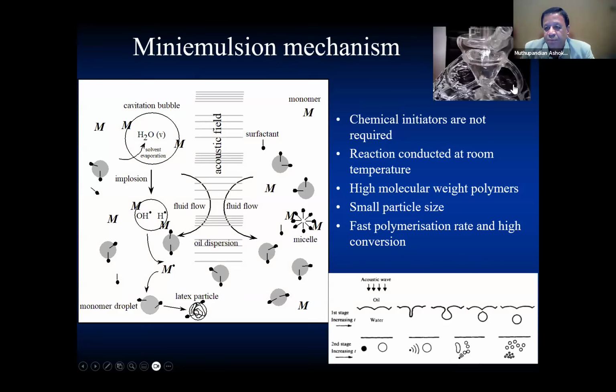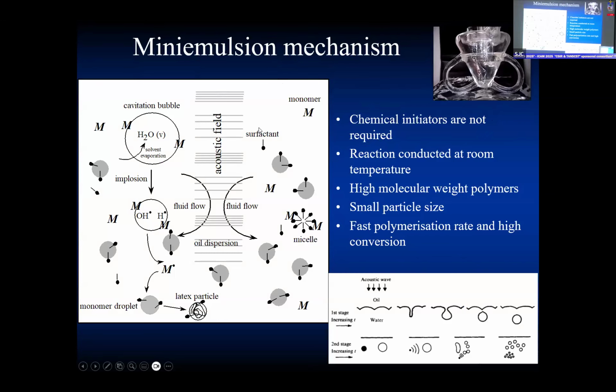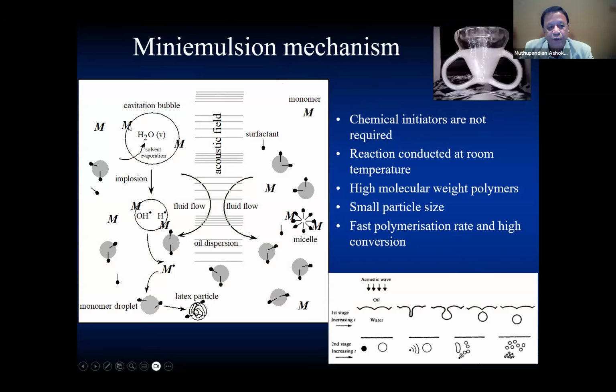So I think I already showed you the picture of how to make an emulsion, for example. When the monomer is dispersed using this emulsification process that you saw, you get the monomer droplets, and then you have, in water, cavitation bubbles generating radicals. Radicals then can react with the monomer to generate monomer radicals. The monomer radicals can diffuse into the monomer droplet to convert them into polymer particles. So by controlling the size of the monomer droplet, I can control the size of the polymer and also the molecular weight of the polymer.